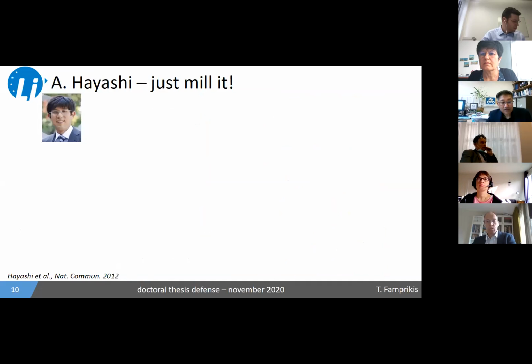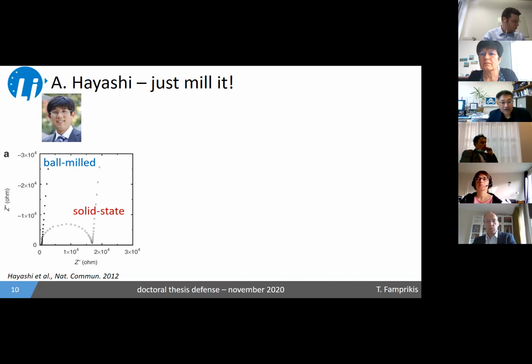So the reinvigoration of the interest in Na3PS4 came 20 years after the first study by Janssen, from the work of Akitoshi Hayashi, who showed that if you produce the same material, Na3PS4, by ball milling, you can significantly reduce the resistance, as shown in the impedance spectra here. So increase its ionic conductivity.